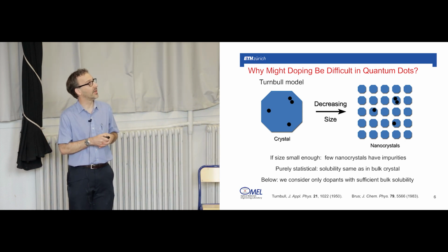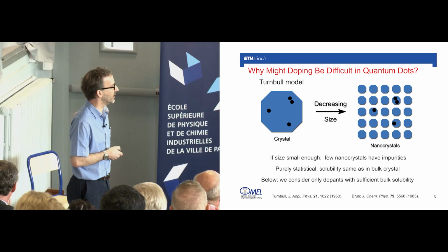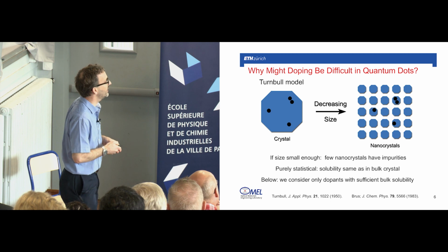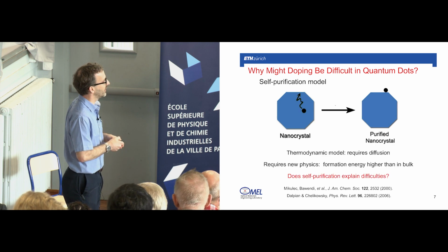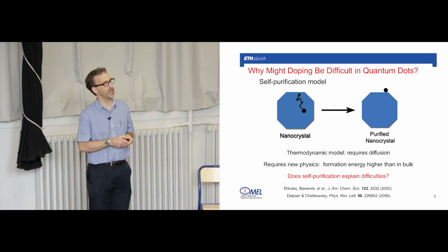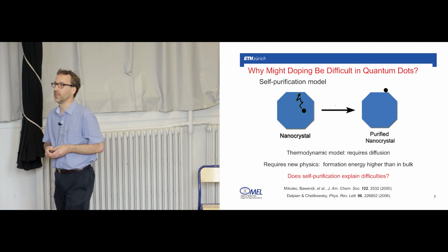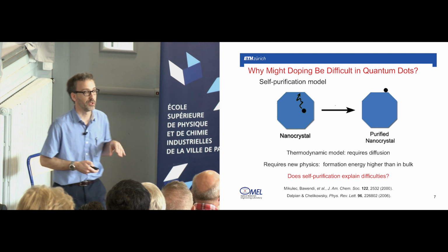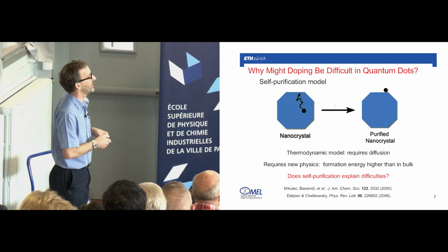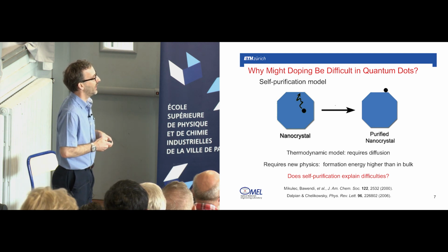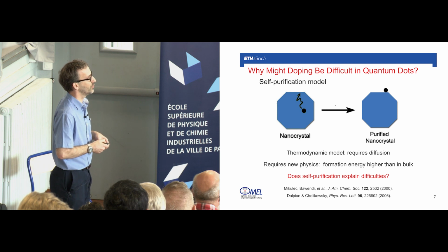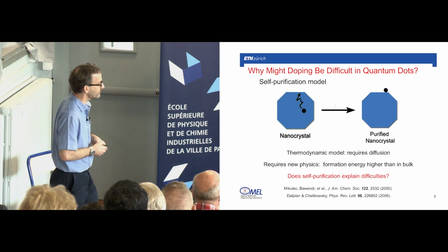Now, another very common model, this very common model is the self-purification model, which has been very alluring over the years. And it argues the following: if I have a nanocrystal that has an impurity inside of it, it's always just a few lattice constants from the interface. So if there's any kind of thermodynamic driving force to push that impurity to the surface, that will happen, and the particle will self-purify, and you'll squeeze out this impurity.